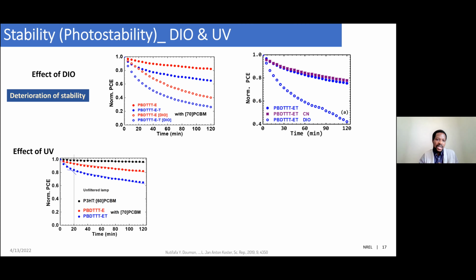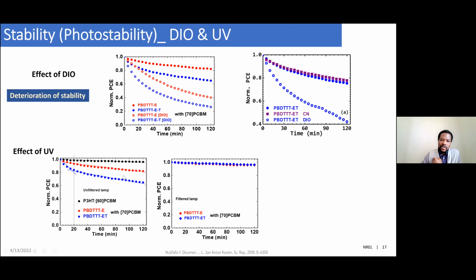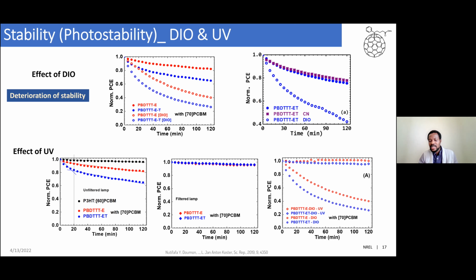So we try to understand that, and what we did is to sieve the UV part of the solar simulator. And here clearly you can see from the initial curve, when you filter the UV part, you realize that your devices retain a very good level of stability. So the conclusion is that it's the UV part of the light that causes this degradation, which is not new because it's already known in the literature. But for us, in terms of DIO, that's the significant observation.